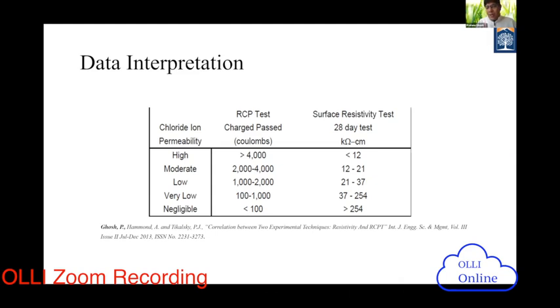So they are correlated with surface resistivity. More than 4,000 coulombs of charge, less than 12 kilo ohm centimeter of surface resistivity, they are equivalent. So indirectly, we are correlating surface resistivity with the charge pass. So our aim is to go very low charge pass, which is basically 100 to 1000 coulombs of charge, and resistivity 37 to 254, which we got with different materials that we talked about.